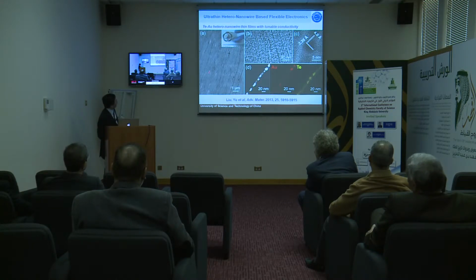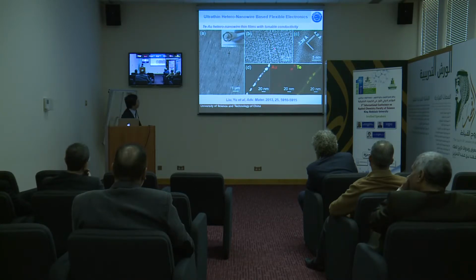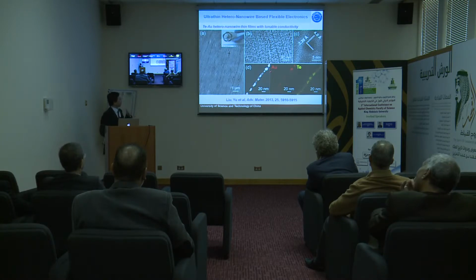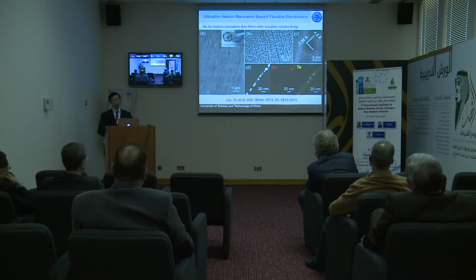We use our highly oriented nanowire assembled structure. You deposit the nanowire ultra thin film onto the flexible substrate, almost transparent. You can deposit in the gold acid for a few minutes. You will see these black dots sitting on the tellurium nanowires, because our tellurium nanowires are very reactive, right? So that you can get this hybrid system. Then you can identify this gold appearance, gold nanoparticles sitting on this backbone of the nanowires, so that you can